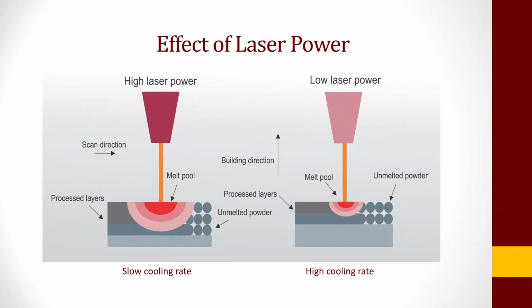I'm going to briefly talk about the effect of laser power. So I have 2 diagrams here. Once you have a high laser power, you could see that the melt pool is much bigger. So once the melt pool is much bigger, which means that it will have a very slow cooling rate. Similarly, when you have a low laser power, the melt pool is going to be small, but that also means that we will have a very high cooling rate. So every time you choose the laser power, you need to look into whether you need a very slow cooling rate or a high cooling rate, so on and so forth.